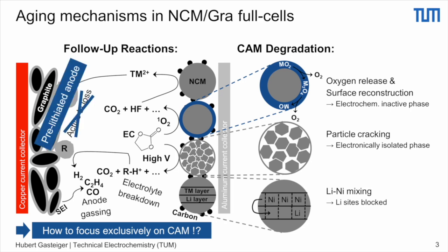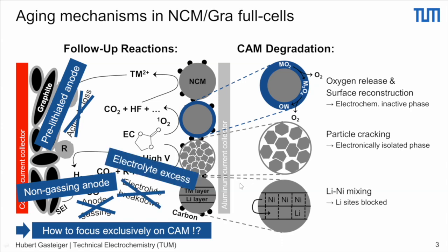And so what we do is we try to use a pre-lithiated anode. In order to eliminate constraints which come from the active lithium loss on the anode electrode, we use a non-gassing anode in order to essentially eliminate the contributions from the anode to the gas signals. And we use an excess of electrolyte in order to not have to consider the continuous consumption of the electrolyte.